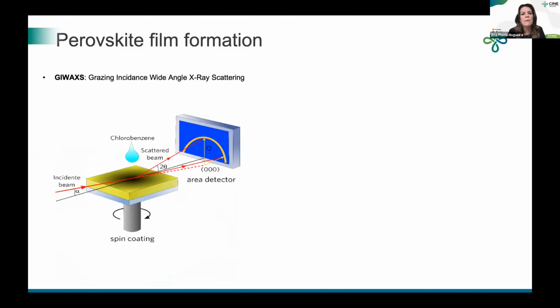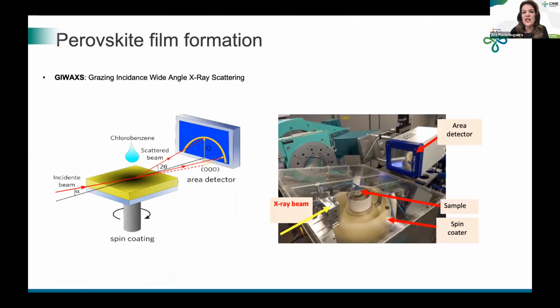Then we went back to the synchrotron, now operating the GIWAXS in situ mode. It was a very interesting experiment, because we brought the spin coater from our lab. We set the spin coater on the beamline, where we could control from outside the time to inject the solvent, or the time to turn on the nitrogen flux. So this is the spin coater. The X-ray beams come from this side. You have our detector, and the sample is here.